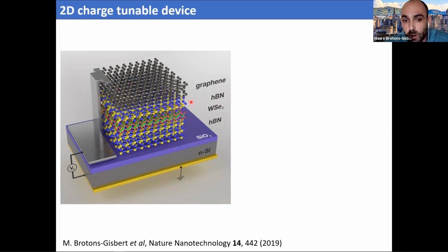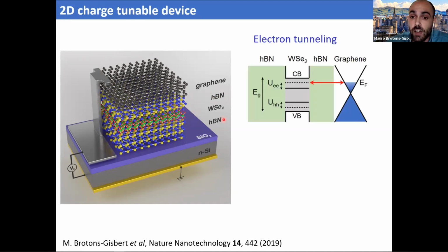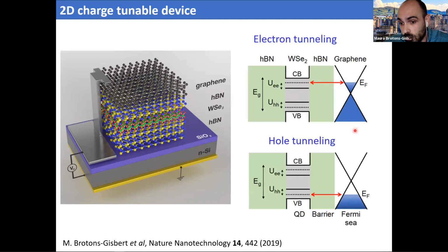And here I'd like to point out something that will be important for the results later, and that is that we decided to make this hexagonal boron nitride layer one atom thick. So that means that our tunnel barrier is one atom thick, okay? And our idea with this device was the following. By using graphene as a top contact, we wanted to have the chance to load both additional electrons or holes in the same device, okay? Which is not possible with conventional III-V quantum dots.